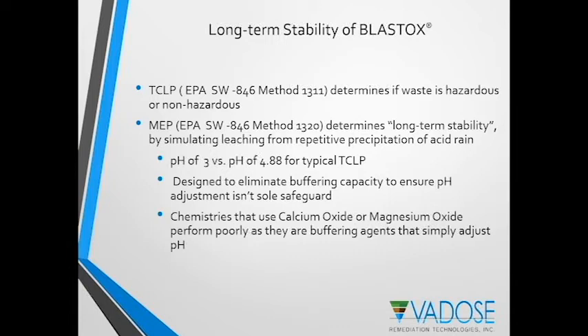This test is designed to eliminate the buffering capacity that comes with a pH adjustment, so that it demonstrates that the pH adjustment isn't the sole safeguard preventing leaching. Some chemistries, such as calcium oxide or magnesium oxide, have performed poorly as they are strictly a buffering agent and simply adjust the pH. Once that pH buffering capacity has been exhausted, then the leaching will begin.